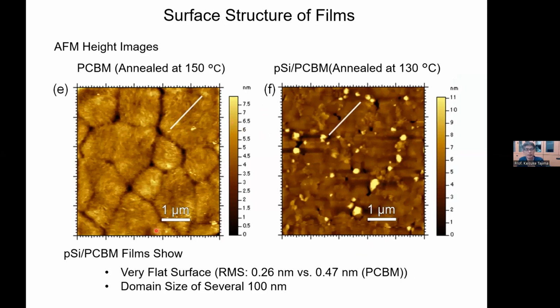This annealed PCBM film is crystallized, so you can see the domains here, and you can even see the hair-like crystal structure here, microcrystals or nanocrystals. But if you put the surface segregated monolayer on top, after crystallization you can see that the surface is much flatter than in this case. So the surface structure is apparently very different, and the crystal domain has a different shape too.